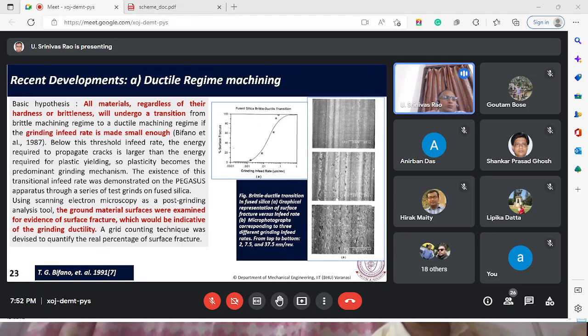So the basic hypothesis in this, whatever we have discussed, is that regardless of the hardness or brittleness, there is a small element of transition between brittle machining regime to ductile regime. So if we can control that, if we make the grinding in-feed rate small enough, then we can achieve the ductile regime machining. And the main advantage of that is the percentage of surface fracture obtained is very less.